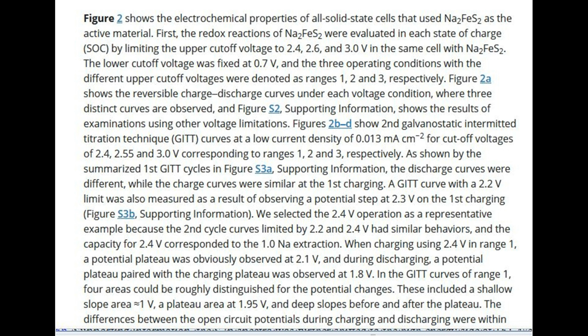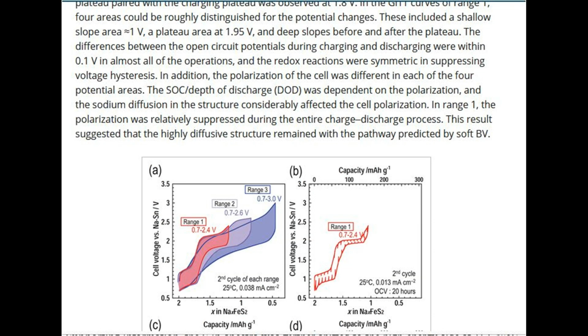In the GITT curves of range 1, four areas could be roughly distinguished for the potential changes. These included a shallow slope area ≈1 V, a plateau area at 1.95 V, and deep slopes before and after the plateau. The differences between the open circuit potentials during charging and discharging were within 0.1 V in almost all of the operations, and the redox reactions were symmetric in suppressing voltage hysteresis.